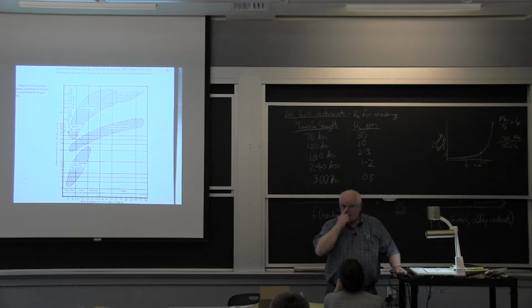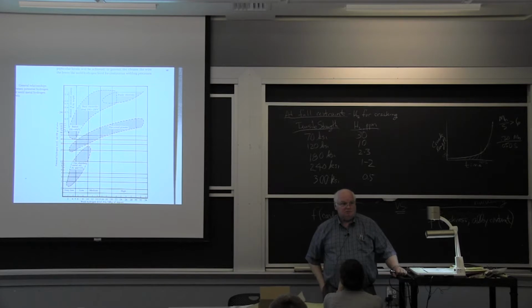If you left a stub out there, they have had pressure vessels in pressure vessel shops blow up because some guy left a 3-inch stub on the ground and some other guy came along 2 days later and welded with it and created a hydrogen crack. And the vessel blew up later. If you're being audited by the ASME code inspectors and they see a stub on the ground, you lose your license. Okay? It's serious. In a Navy shipyard, they count the stubs when you come back to get extra electrodes.